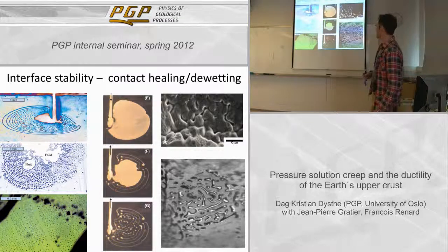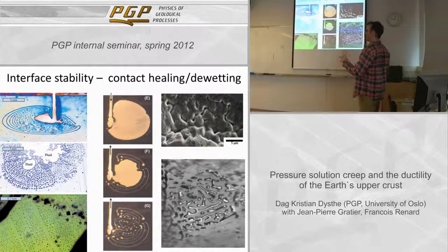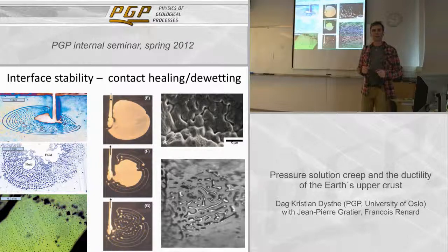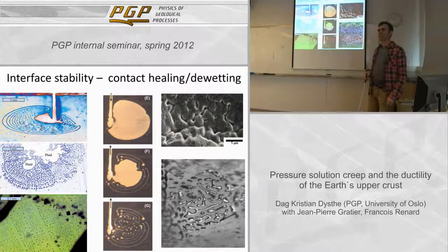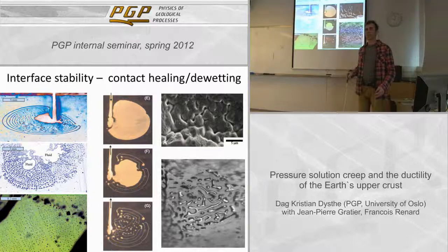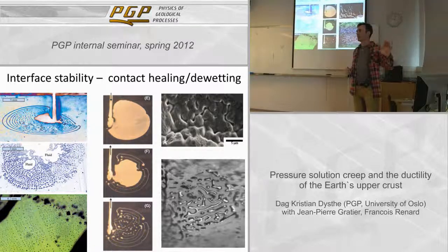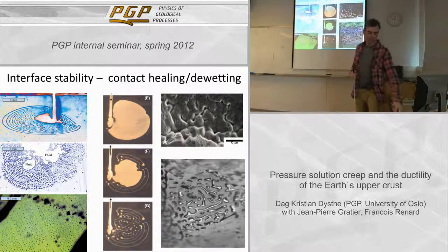And I'll just end by saying that 100 years of pressure solution research has focused completely on only the three-step process: dissolution, transport, precipitation. And there has been a little bit of discussion, but we've never really discussed the implications of, well, what actually happens if the grain boundaries start healing. If you've got an aggregate with a million interfaces and then a network of them starts healing, meaning that the process of pressure solution is closed down and it stops.